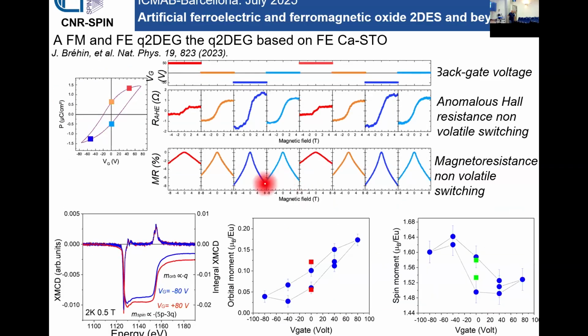And maybe more importantly, if you perform a gating experiment along the ferroelectric loop of the bulk calcium-doped STO, you can measure the anomalous Hall effect component and the magnetoresistance. You can see that there is a modulation of the properties, but the modulation is non-volatile, because if you go from P down to P up polarization, you see that the change of the anomalous Hall effect and magnetoresistance is non-volatile. I mean, at zero gate, you can get a non-volatile change of magnetotransport properties.